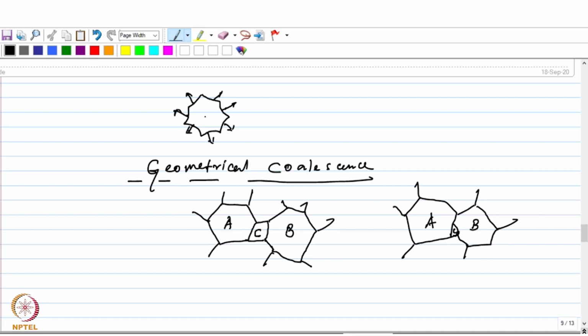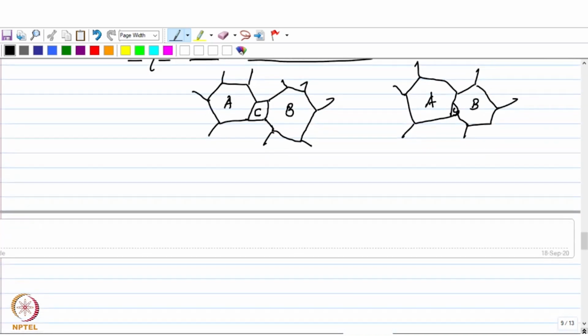And as that happens, there are two possibilities with regard to the boundary that separates these two grains. Okay, so it is quite obvious from here that A and B are more favorable for growth compared to C, because you can see the number of sides for C is much lower compared to A and B. So C is going to shrink and A and B are going to grow, right? As you could see from here also. So ultimately this smaller grain C will disappear and there will be a boundary developed between these two grains A and B. Okay. So with regard to that boundary, there are two possibilities.